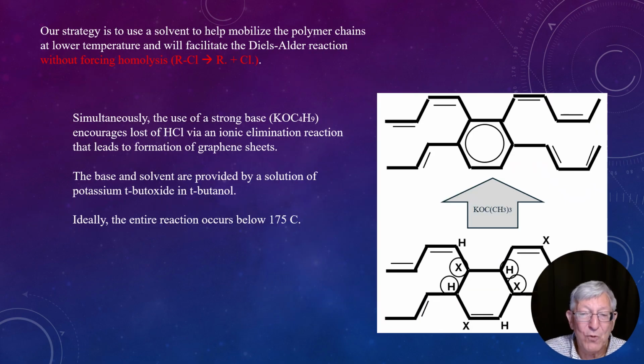And the idea is, okay, we're going to try to fluidize these polymers by using a solvent. And so our strategy is to use a solvent to help mobilize the polymer chains at lower temperature that will facilitate the Diels-Alder reaction without forcing homolysis. We still have to get rid of the HCl. And the way we're going to do that is not by having a homolysis, not by having a free radical reaction. We're going to use a base, potassium t-butoxide, to pull off the protons and kick out the halides, such that this is a reaction that is not going to go by a free radical mechanism.